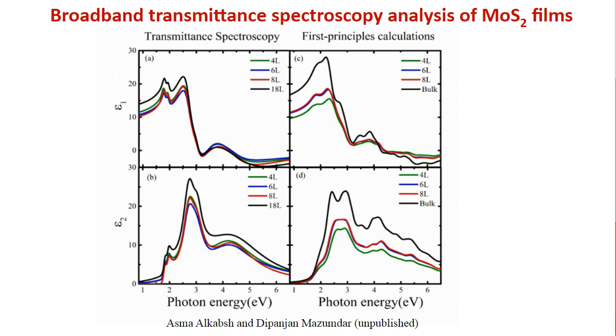On the left-hand panel, the top and the bottom, I'm showing the experimental data that is obtained using transmittance spectroscopy, using our spectrometer. And on the right, I'm showing the first principles calculation that is done with a technique called density functional theory. This is a theory that's employed by physicists and chemists and material scientists to calculate the electronic structure. Now, what we are doing here is really a direct comparison of the experimental data to the theory data.